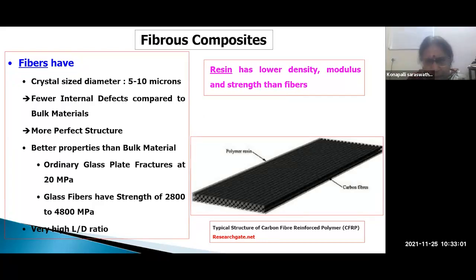Fibers actually have a very small crystal size, diameter 5 to 10 microns. The lower the size, the fewer the internal defects, the better the properties compared to bulk, and we get a more perfect structure. If you see an ordinary glass plate, fracture toughness is very low, 20 MPa. Once you draw glass fibers, we can get fiber strength in the fiber direction from 2800 to 4800 MPa. That is R glass, very high strength, up to 4800 MPa, because of a very high L by D ratio. So we get very high properties of fibers compared to bulk form.